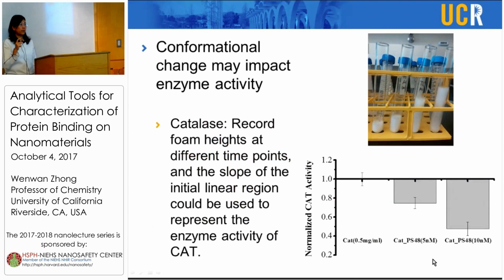And then we suspect the heme group is why all of the heme-containing proteins we find actually show very large fluorescence change, because the heme group has the iron. And the iron could possibly act like a metal bridge between the protein and the aromatic polystyrene particles, and once the heme group is changed, it will change the lysine hydrogen bonding with the peripheral amino acid side chain that will open up the protein structure and enhance more labeling.